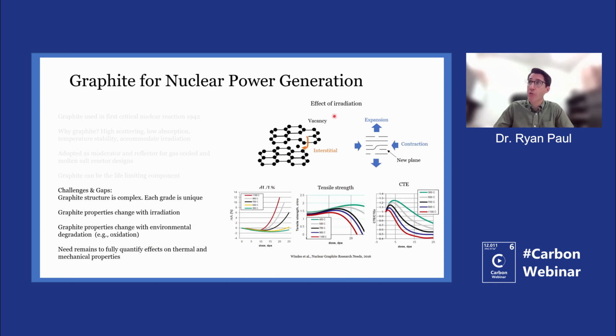So irradiation is one important one, as high energy neutrons from a nuclear reaction hit a graphite lattice, they can knock out carbon atoms into an interstitial position. If you do this enough and you form enough vacancies and enough interstitials, you can get expansion in one direction and contraction in another direction of the graphite lattice. And this is at the crystallite scale, the very small scale. Of course, there are effects occurring at the microstructure scale as well.